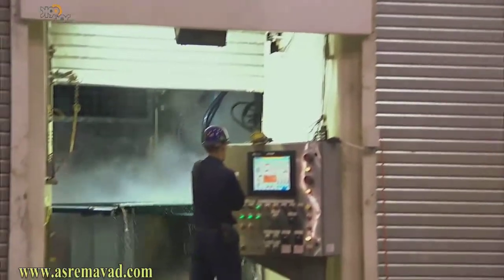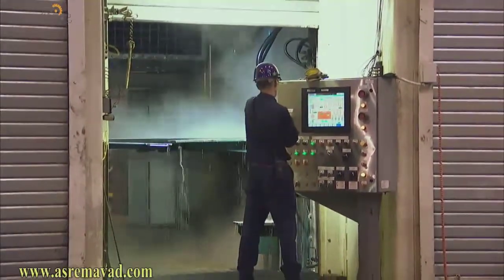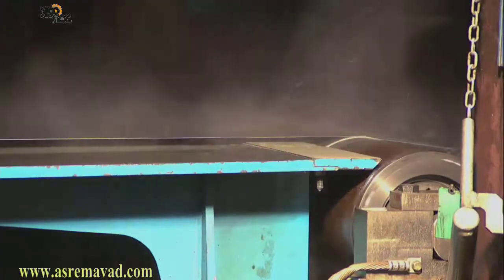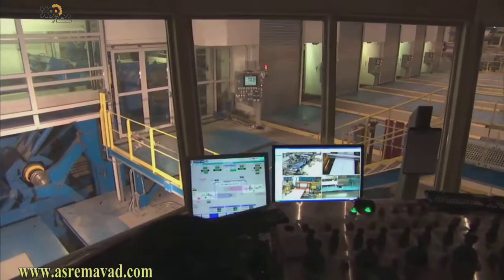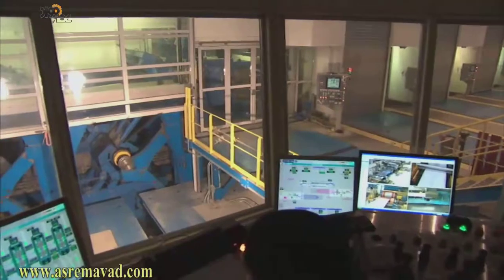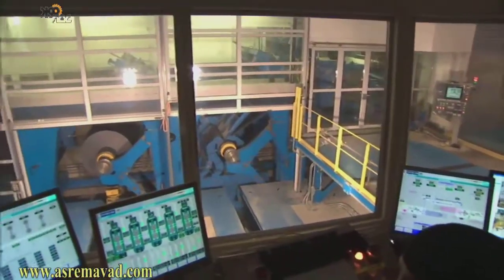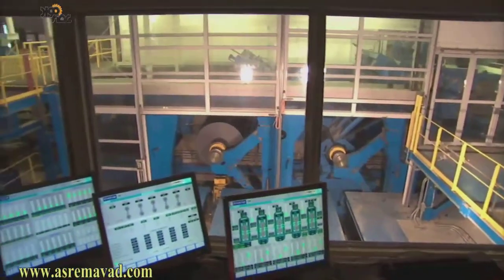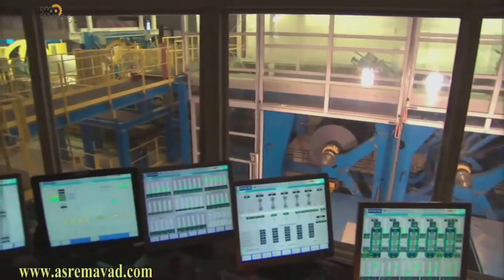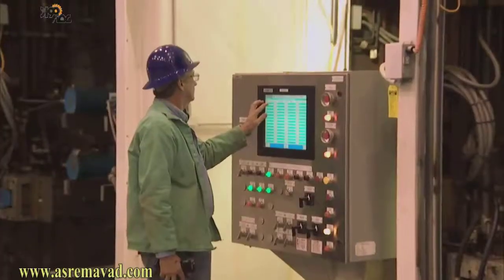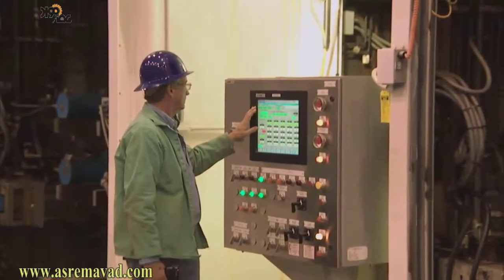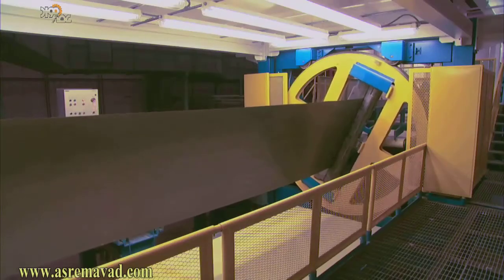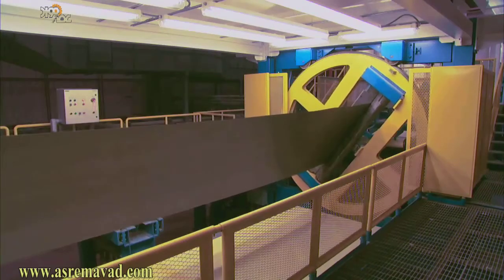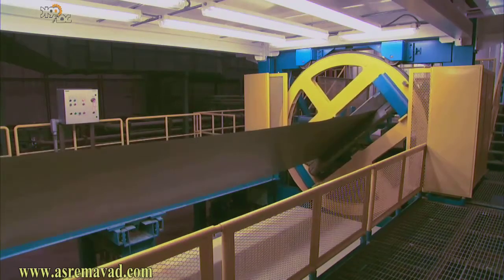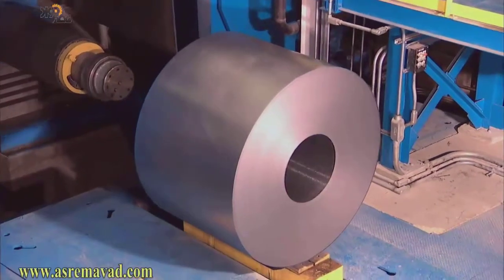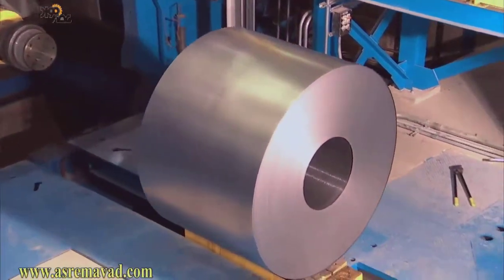After pickling, the coils may be further reduced in a cold rolling process. Each cold mill rolling stand successively reduces the thickness to a final gauge ranging from 0.014 to as heavy as 0.074 inches, or the approximate thickness of a nickel, again depending on the customer's order. The mill features a closed-loop gauge and shape control system, and a 360-degree rotating inspection table to ensure the highest quality surface and shape. At this stage, the coil is a full hard cold roll product primarily sold for roof decking.